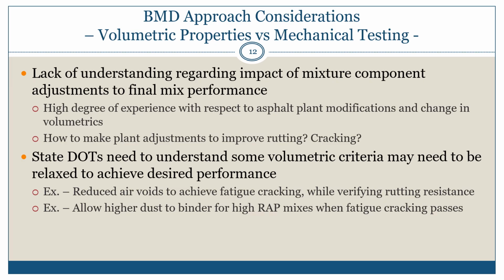Also, state DOTs need to understand that some volumetric criteria may need to be eliminated or relaxed to achieve some desired performance. A number of our interviewees spoke about reducing air voids to allow greater asphalt contents, allowing dust to binder content to possibly be a little bit higher for RAP mixes that are still meeting a fatigue cracking test. And a lot of that is based off of the experience and how well the agency feels regarding the test method itself and the confidence in the criteria. So things to understand moving forward is that volumetric criteria does still play a role in how we make adjustments. They're not going to tell us everything about cracking and rutting, and some of these volumetric criteria may need to be relaxed in order to make sure that we can make a good performing mix.